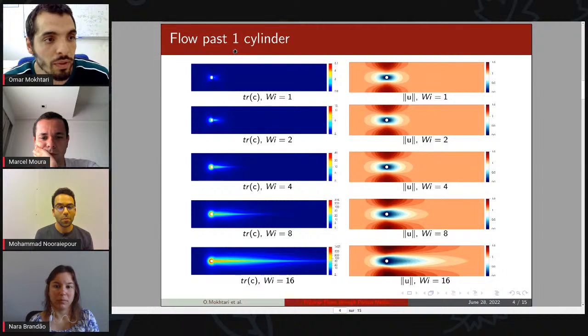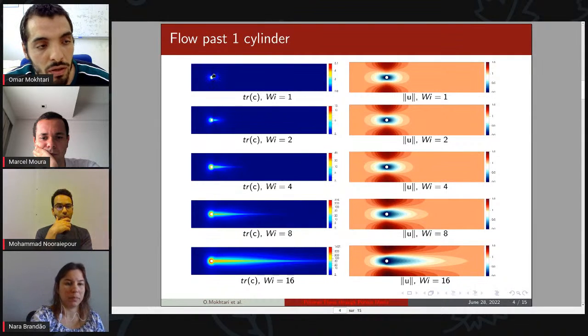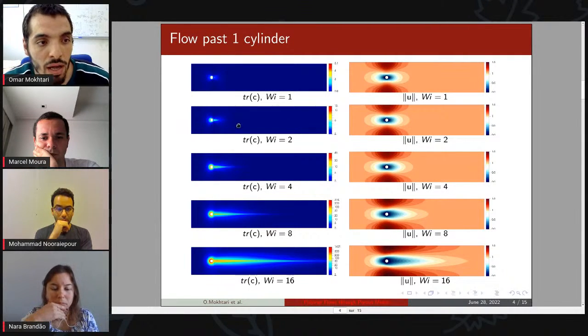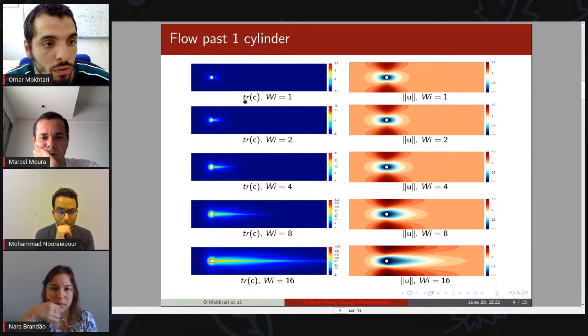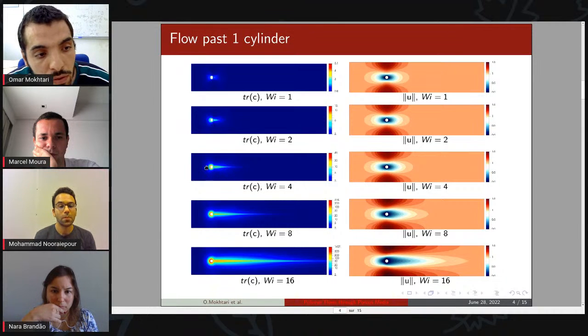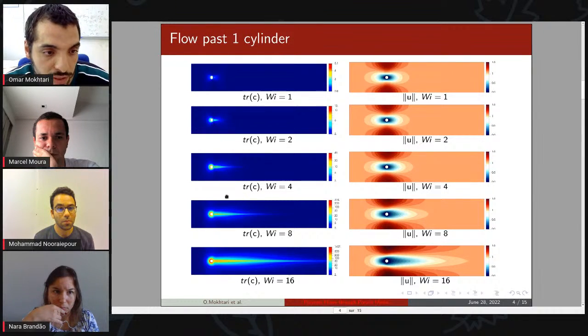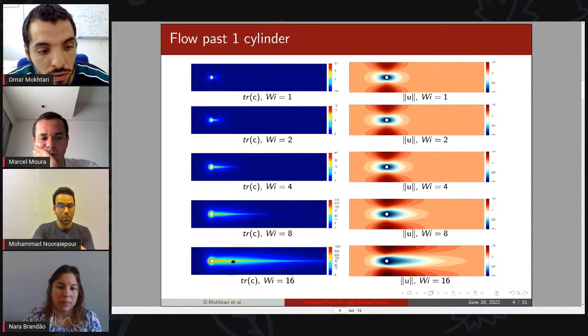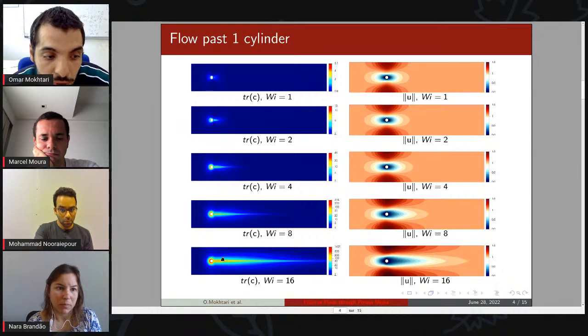So we first consider the flow past a single cylinder. We impose biperiodic conditions, and we increase the Weissenberg number. On the left, we can see the trace of the conformation tensor, and by increasing the Weissenberg number, we can see the appearance of a strand in the wake of the cylinder, which increases almost linearly with the Weissenberg number. This corresponds to highly elongated polymers, and these polymers act as a tangential force opposite to the flow.